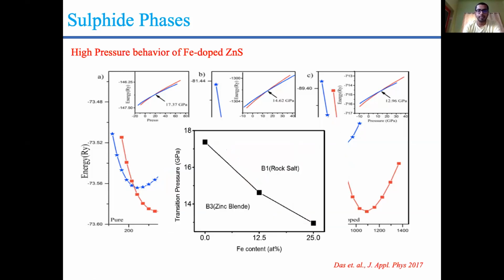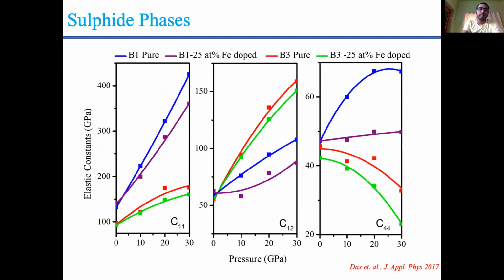If we draw the phase diagram with iron concentration, we see an inverse relation with the increasing Fe content. But this is a preliminary work that I have started with. Our main aim is to investigate their mechanical and electronic properties. To start investigating their mechanical properties, I started with the elastic constants.